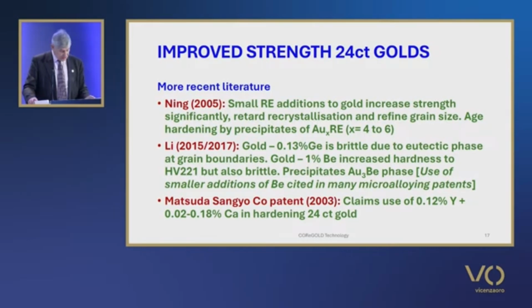The as-cast grain size was refined and the microstructure comprised gold dendrites and eutectic phase of gold and the gold 3 beryllium intermetallic. The phase diagram indicates there is almost no solid solubility of beryllium in gold. This work has relevance to microalloying since the use of smaller additions of beryllium are cited in many of the patents.